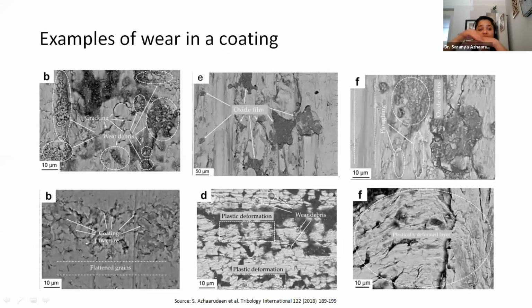Ploughing means it's like ploughing the field, where the material is removed like a plow from the field. And oxide debris is also, as you see from the second picture, a kind of debris formed from the oxide film. And in the fourth picture, you can see the fracture. I mean, the coating has been fractured, and there is also flattening of the grains, because the grains are there and something is going over the surface and the surface has been flattened.